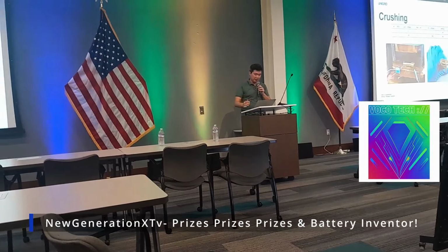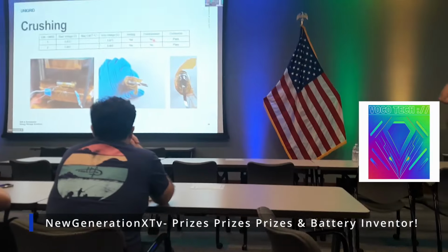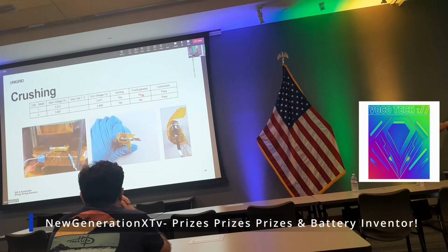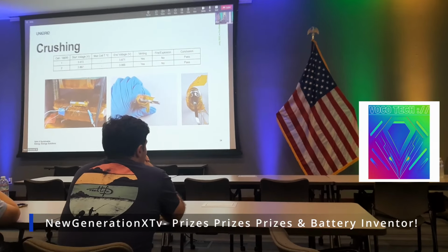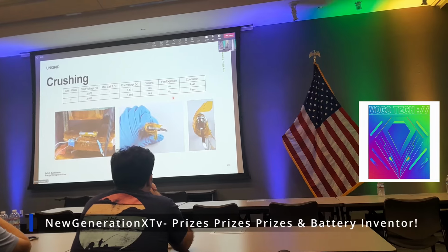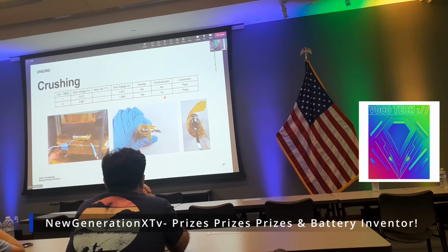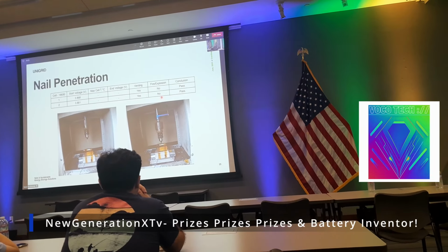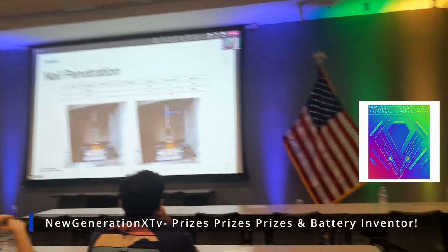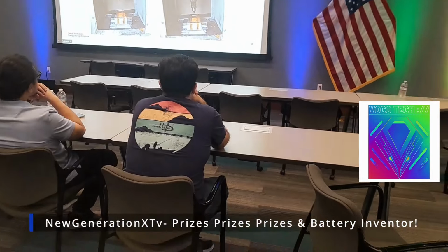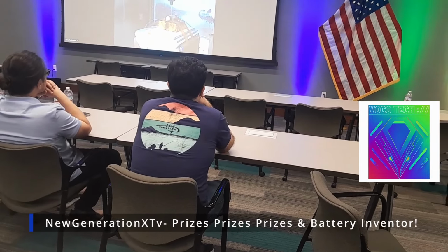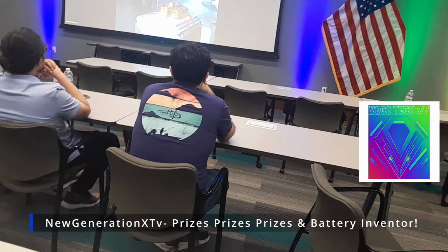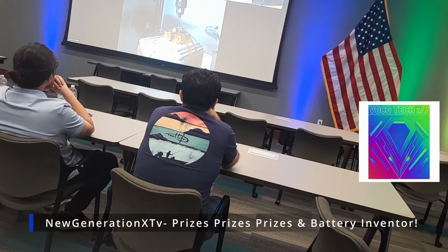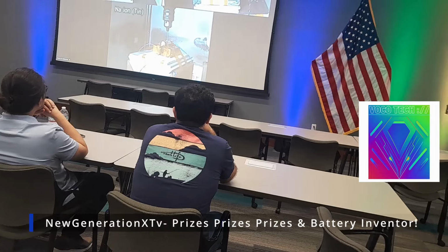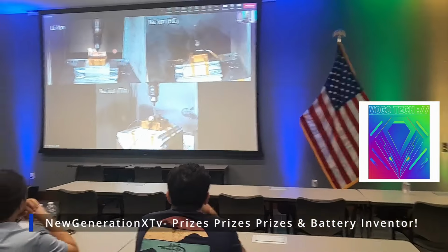We also crush the battery, so we use a hydraulic press like those you see on YouTube. It presses it into kind of a potato shape. No nasty things occur. We also do a nail penetration, so this simulates something mechanically destroying the cell. We have a couple of videos from there as well. So let me interpret what's happening here. In the top left-hand corner, we have a lithium-ion battery that's being penetrated, and you see it burst into flames. The temperature rises to about 600 to 800 degrees Celsius.